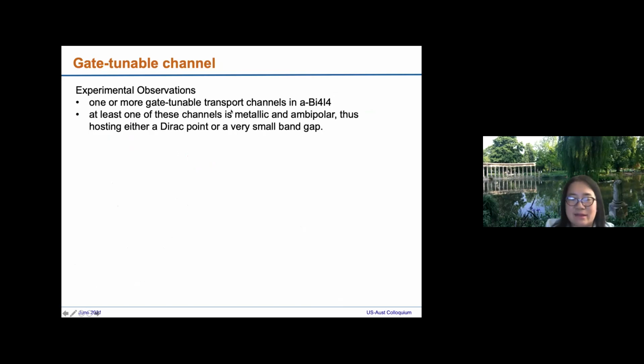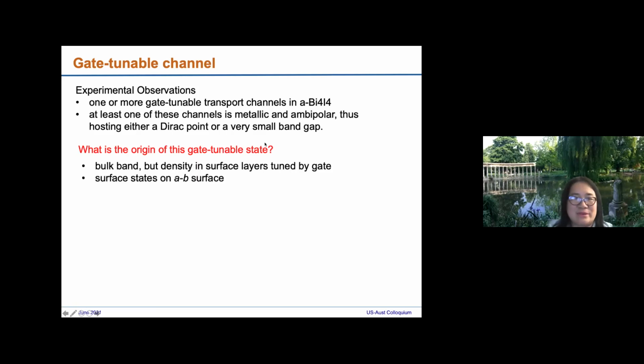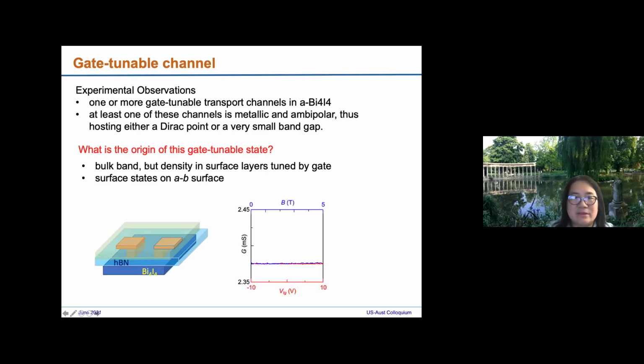This is the experimental observation: we have some gate tunable transport, and at least one of these channels is metallic and ambipolar, so it either has a Dirac point or a very small band gap. Now we have to be a little bit speculative. What is the origin of this gate tunable state? We think maybe it's a bulk band, but with the density in the surface layer tuned by the gate. Or we can have a surface state on the AB surface.